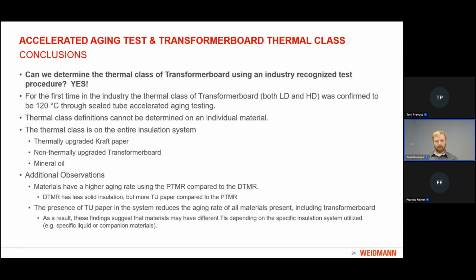So finally, I want to come back around to Tom's problem statement: can we determine the thermal class of transformer board using an industry recognized test procedure? And the answer to that is yes. For the first time in the industry, the thermal class of transformer board, both high and low density, was confirmed to be 120 degrees C through sealed tube accelerated aging testing. Following an industry recognized procedure, IEEE C57.100, we established a temperature index of at least 110 degrees C, in many cases being 120.